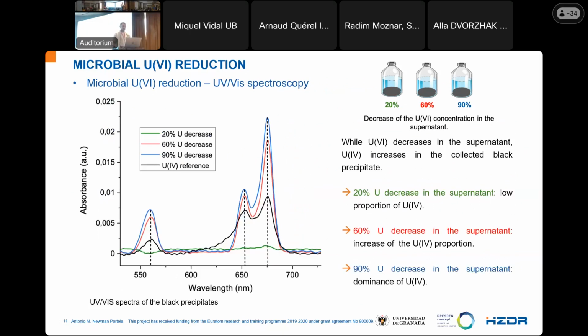So, therefore, we sampled three different samples during the experiment based on the decrease of the uranium(VI) concentration in the supernatant, which is 20, 60, and 90%. And you can observe how the black line corresponds to the reference, and the green, red, and blue lines correspond with the different samples. And with 90% of uranium decrease in the supernatant, we observe a high dominance of uranium(IV).